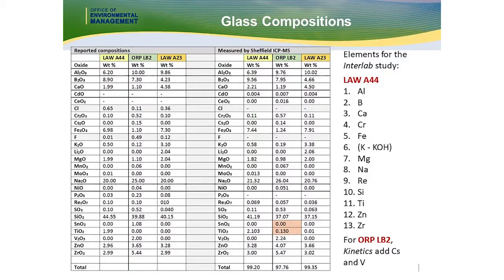So the glass compositions you have over here, LAWA44 and ORP-LB2, which are being used. The important message of what you find is that from the screening studies, this is the list of elements that were readily detectable and distinguishable from the leaching from the glass under all the different glass conditions that were tested. Well above the detection limits for the test methods and the instrumentation being used.